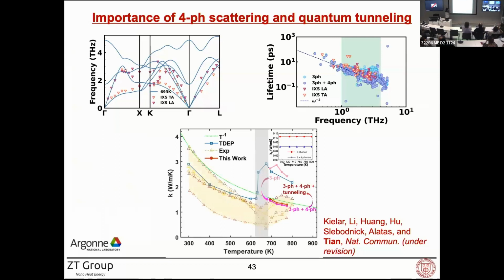Now, if we put everything together for thermal conductivity as a function of temperature, we can see if we only include the three phonon scattering, we're here in the pink. And then if we include the four phonon scattering, we are coming down into this experimental window. We also considered this quantum tunneling effects, but the contribution is very small. So it only moved up the thermal conductivity a little bit. But with that, we are able to bring the calculated thermal conductivity within the experimental range.